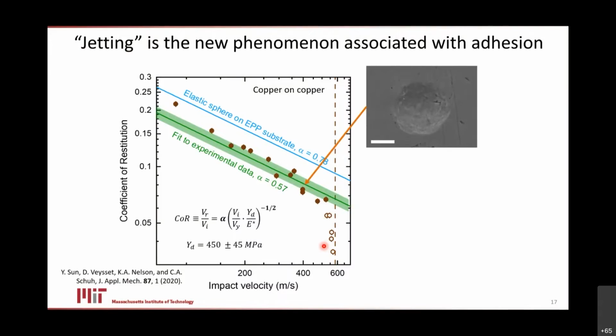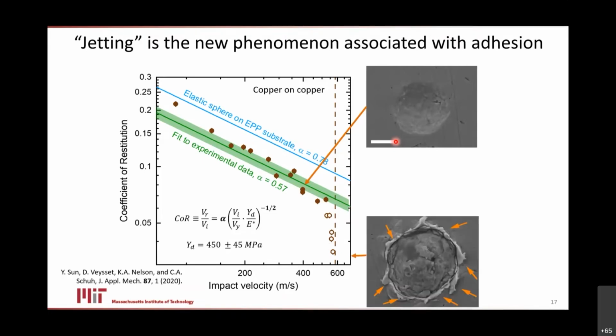So data are great, but they're even better when they're augmented by good microscopy. So let's put these things in the microscope and look at them. Here's what happens in the case where you have what I would say sort of classical power law plasticity. Here we have a crater for copper on copper, and it just looks like a crater. There's no evidence that there's any kind of rupture at the edges or jets of material have shot out. So that's what a clean, no jetting impact looks like.